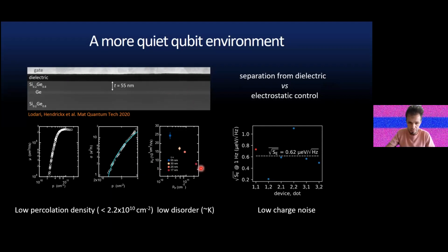Here we see that by burying the quantum well deeper, you get a boost in the two quality indicators, which are quantum mobility and percolation density. So this goes high and this goes low. That's really nice. We are now doing more studies on this platform and also on other platforms like electrons in silicon, to find a correlation in order to control disorder in these systems.